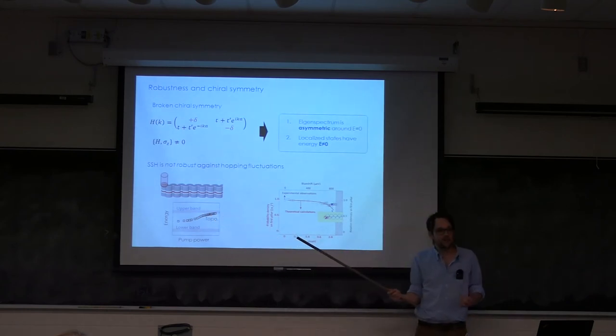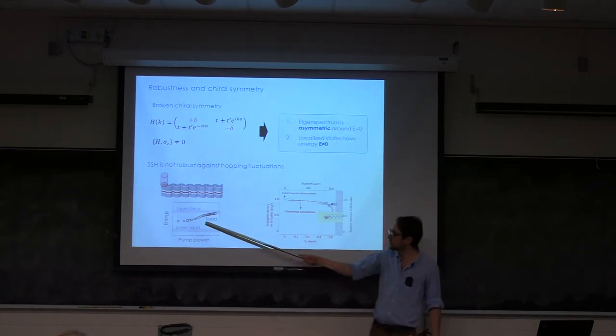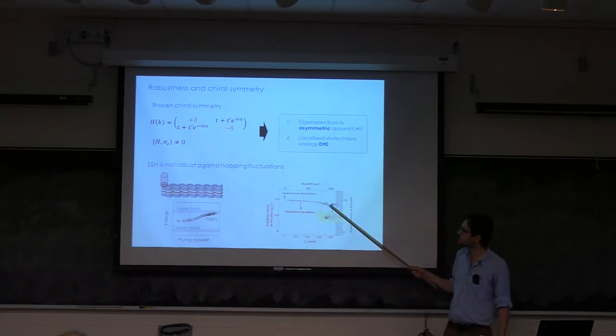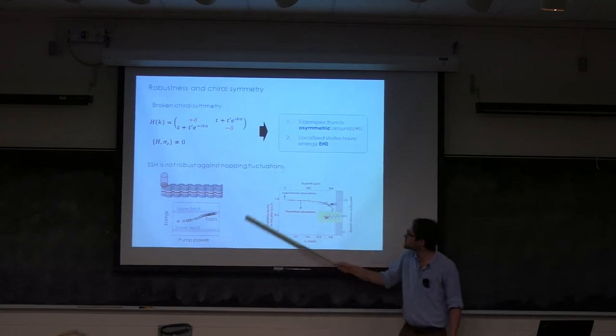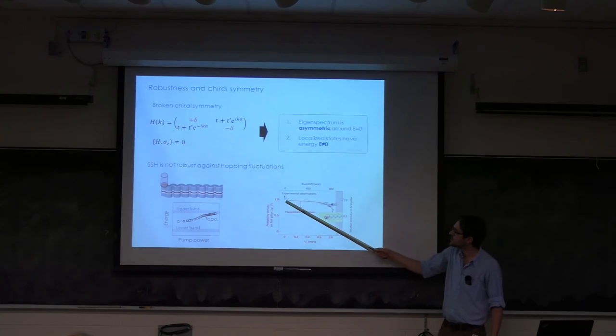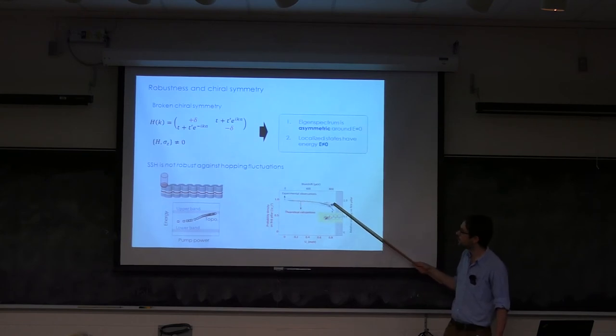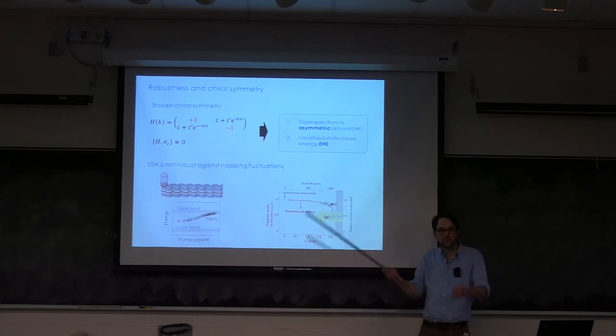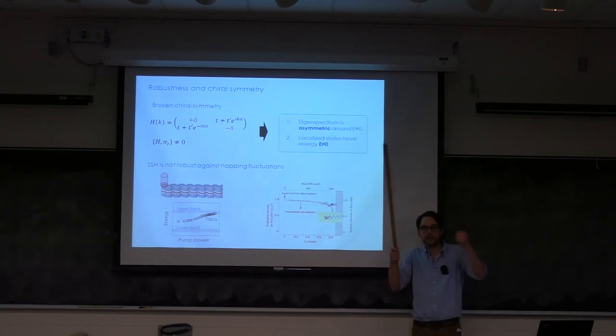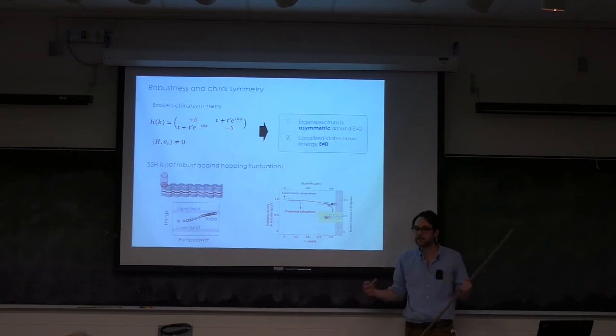And as long as you have this, you're going to have an edge state. It's not going to be at zero, but it's going to be strongly localized at the edge. So we see that here as a function of the pump power. Here, the squares are the experimental data showing the relative intensity of the first pillar. It doesn't change much unless you blue shift your mode so much that it reaches the gap, and then you completely lose it. It hybridizes with the band, and you're not protected anymore, because protection means the perturbation needs to be smaller than your gap. The gap is the energy scale that dictates the entire robustness, quantitatively.